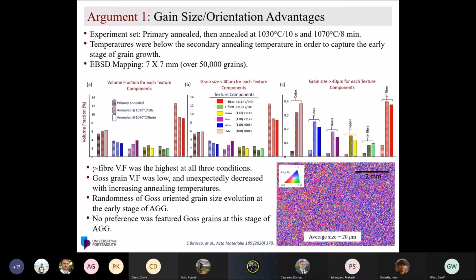In the first set of experiments, we have the primary anneal sample, and we annealed it at 1030 degrees Celsius for 10 seconds only to capture the very early stage of grain growth, and then at 1070 degrees Celsius for 8 minutes. We looked at the 7x7 EBSD mapping, which captured about 50,000 grains. This temperature is selected below the secondary annealing temperature to capture the early stage of abnormal grain growth.